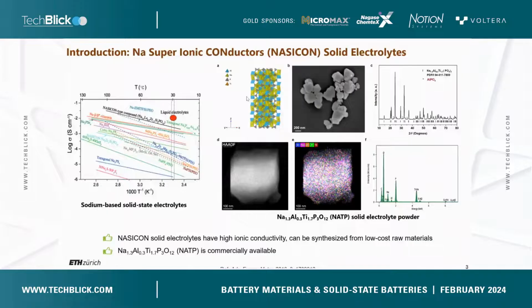There are also other NASICON solid electrolytes like sodium zirconium silicophosphate. All of these materials have a three-dimensional framework with a specific arrangement of the metal oxyphosphate tetrahedrons. The sodium ions are located at the interstices between these layers. This framework allows the sodium ions to move efficiently throughout the crystal structure with very little resistance. And this is quite critical when it comes to the development of fast charging batteries and so on.